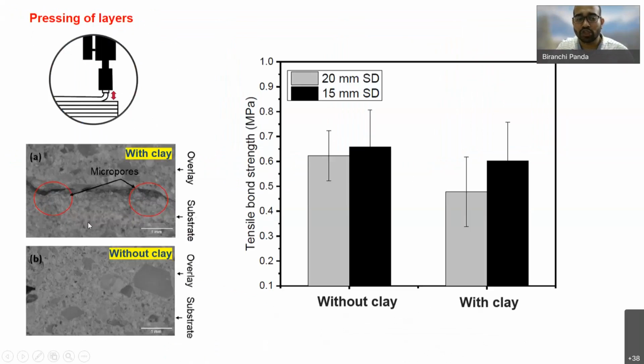The same thing is not going to happen if you have a stiff material, because with a stiff material, even if you press during the printing, there will be some voids which cannot be avoided. And if this material is fresh, then this void can be avoided. As you can see, if you print with a lower layer height, this porosity can be minimized, and of course the reduction of porosity is going to improve the bond strength.